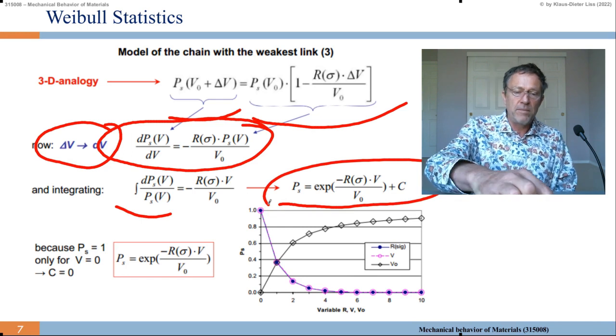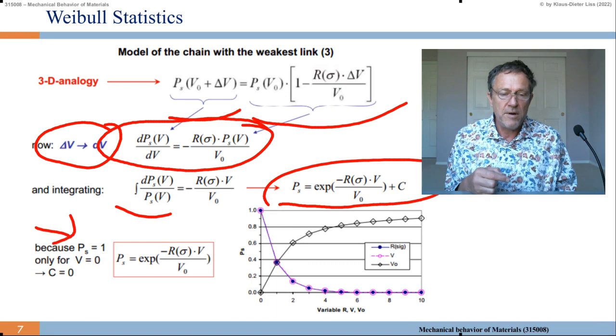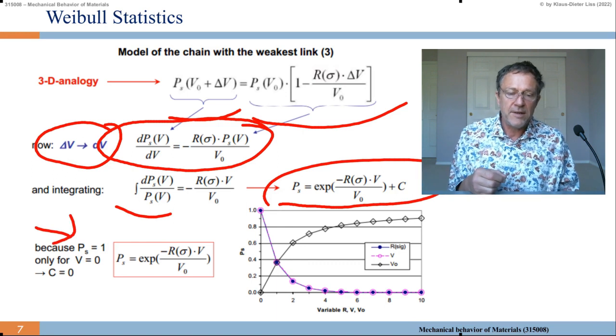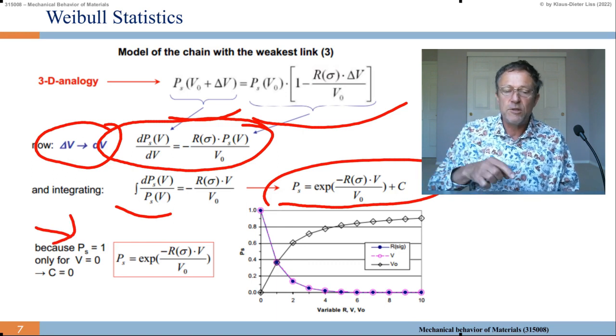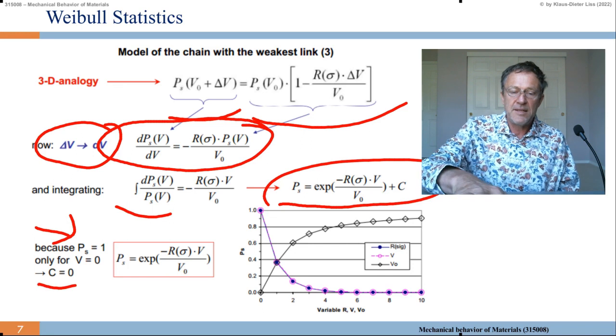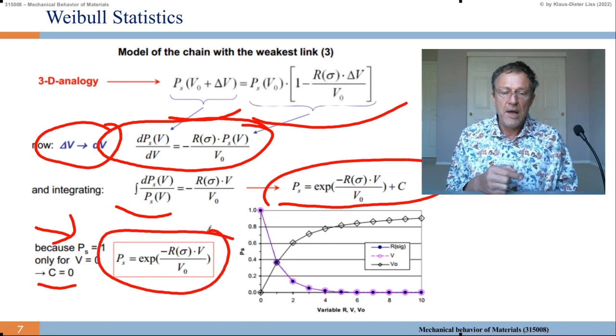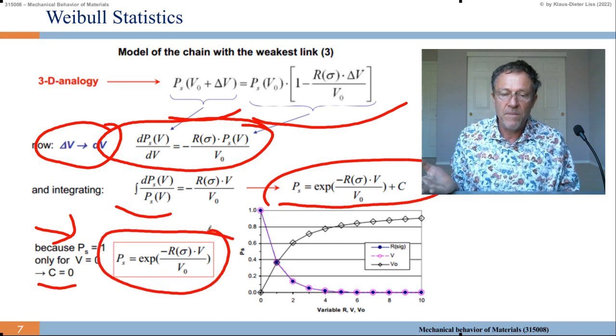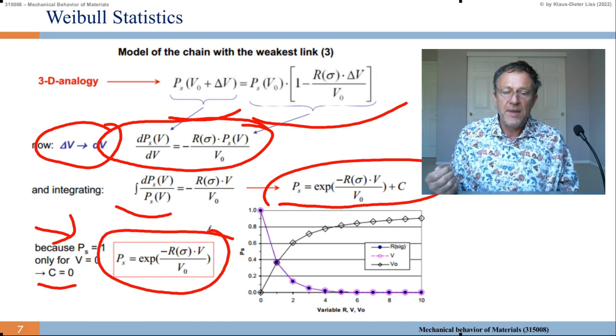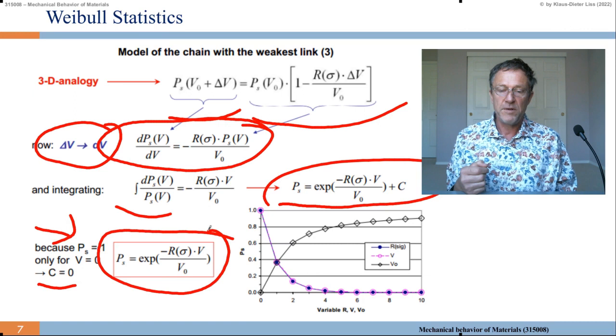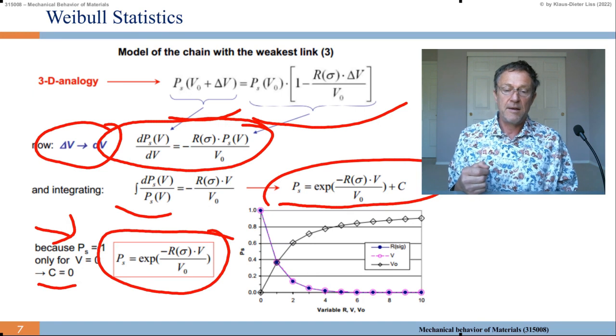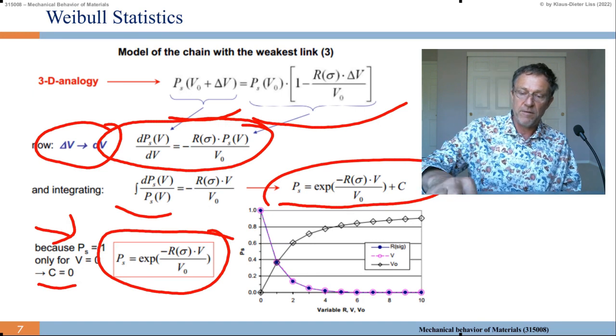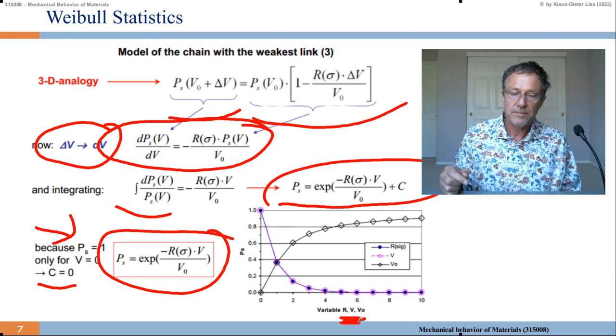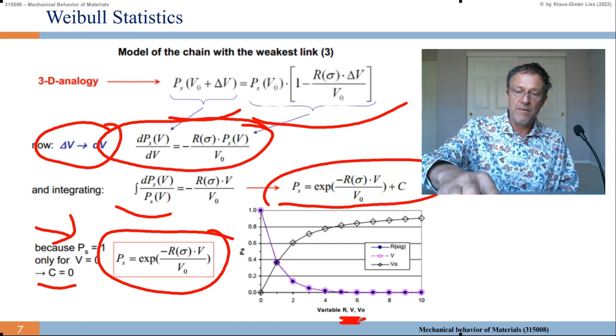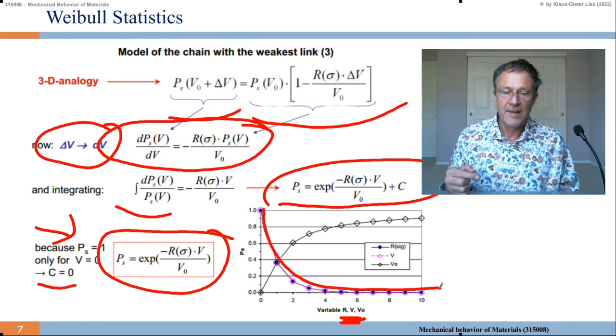And now, because PS equals 1 only for V equals 0, the C has to be 0, resulting here into PS is just an exponential of minus R of sigma times V over V0. So we have a volume V0 to which we normalize, and we vary as a function of V here, and it goes down exponentially.